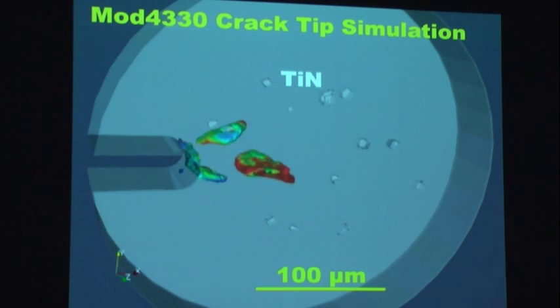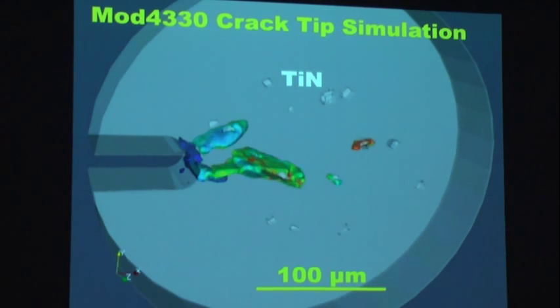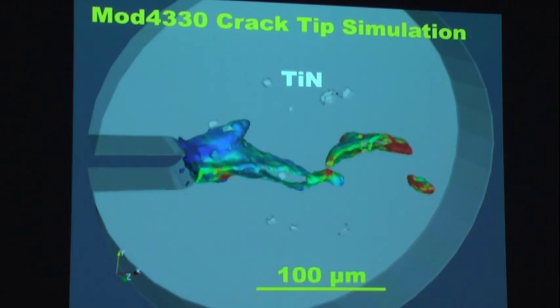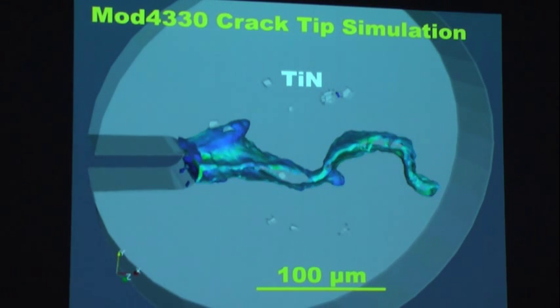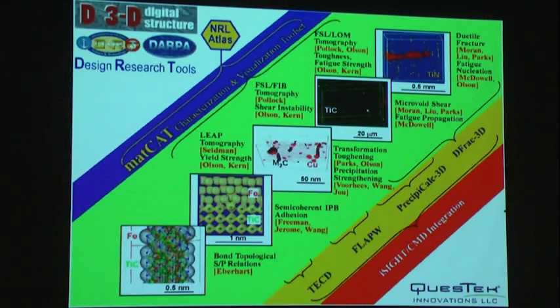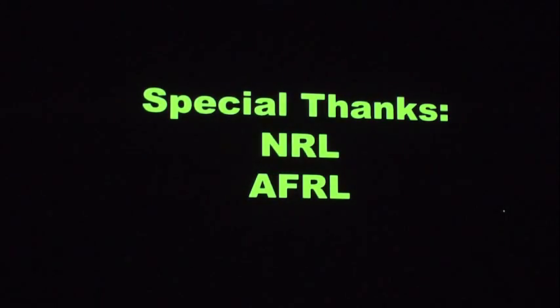We simulate that by putting in a statistically equivalent array of the primary voids embedded in a matrix that has the homogenized constitutive law coming from the submicron microvoiding, and find that we can not only predict the COD toughness, but the actual wavelength of this pattern of shear localization. And so we're well on our way to predicting fracture toughness as accurately as we predict strength. We hope. All right, and this is what we hope to be able to do better with the APS. Thank you for your attention.